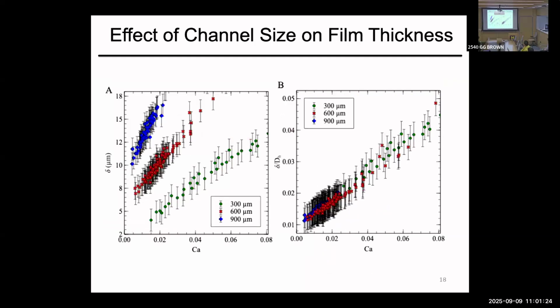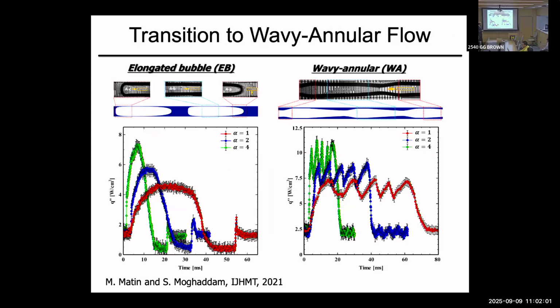So one cool thing is that, as I said, you change the channel size and you think that things will drastically change. But in the framework that we see with this device, this is the thickness of the film, for a range of capillary numbers, for 300 micron, 600 micron, 900 micron. If you divide it by the hydraulic diameter, they all collapse on one line. And that's very much consistent with the lubrication theory, which scales with delta divided by hydraulic diameter versus the capillary number, as you see in the literature.